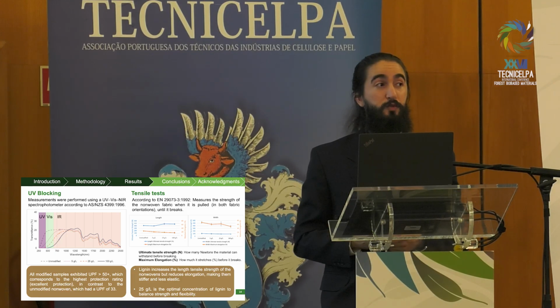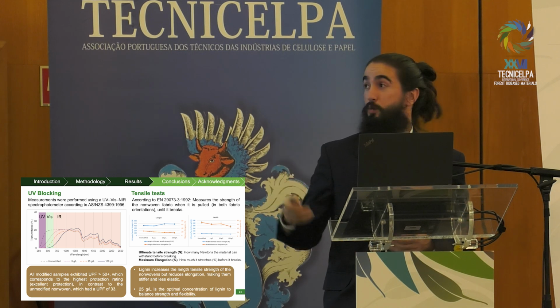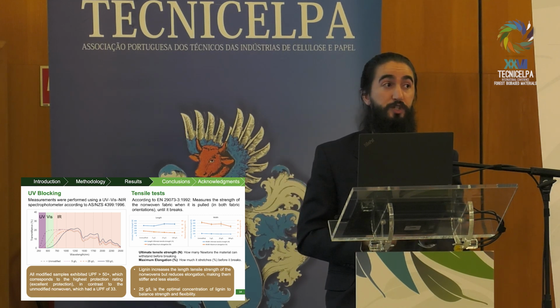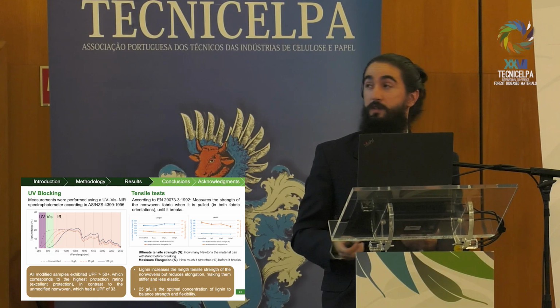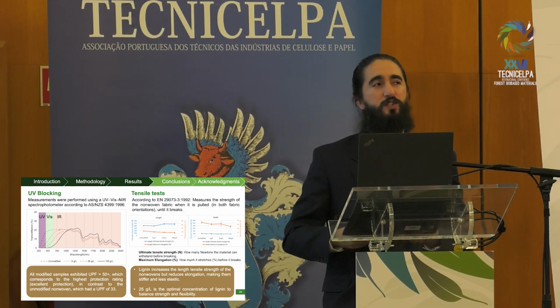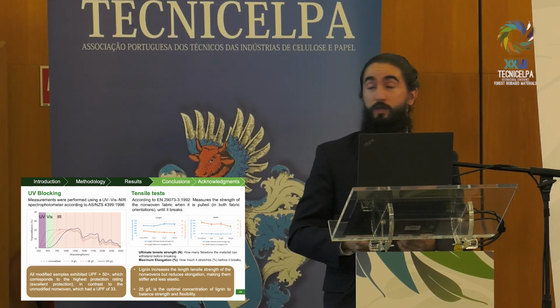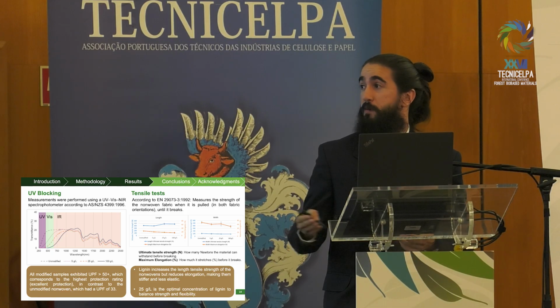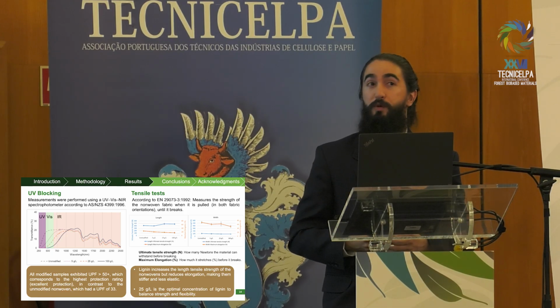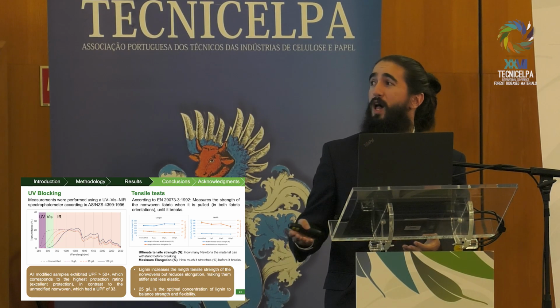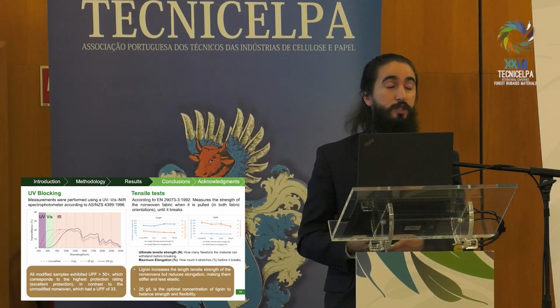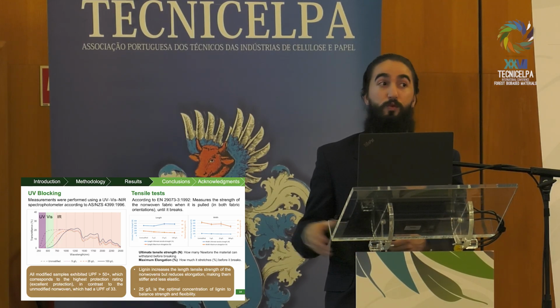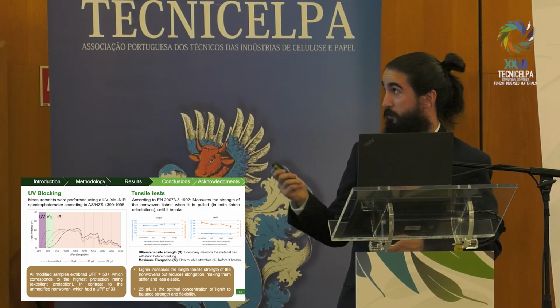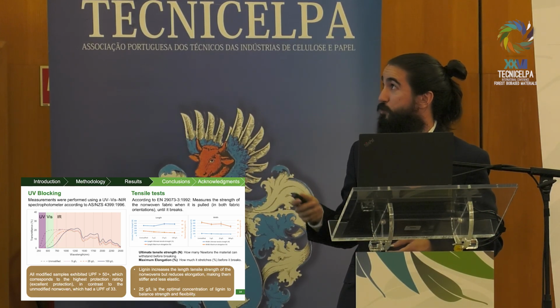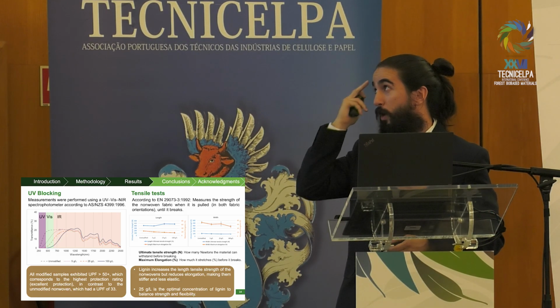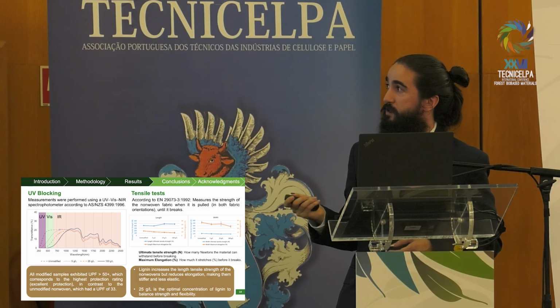And how can we explain these results? Of course, due to the lignin that we have. For example, due to absorption, since it has carbonyl groups in its constitution. Also some antioxidant effects due to the phenolic groups in the lignin, for example, that can neutralize free radicals and prevent photochemical degradation. And also due to the branched and amorphous structure of the lignin, it can also have some reflection or light scattering.